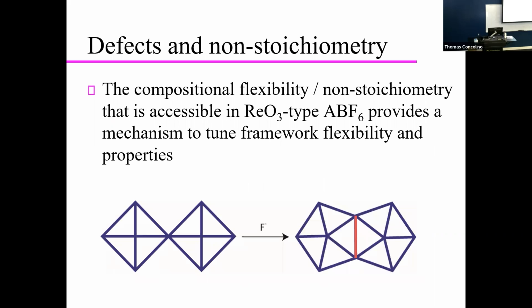Well, it's actually known. It's been known since the 1970s how you can do that for some rhenium trioxide type fluorides. So this is the general recipe. Take our all corner shared structure, add excess fluoride and bake. And you can convert those corner sharing motifs to edge sharing motifs. So that was what we proposed. So that's where the extra fluoride has gone.